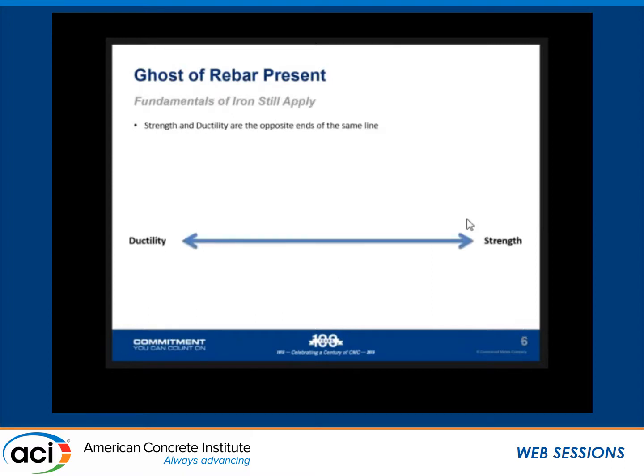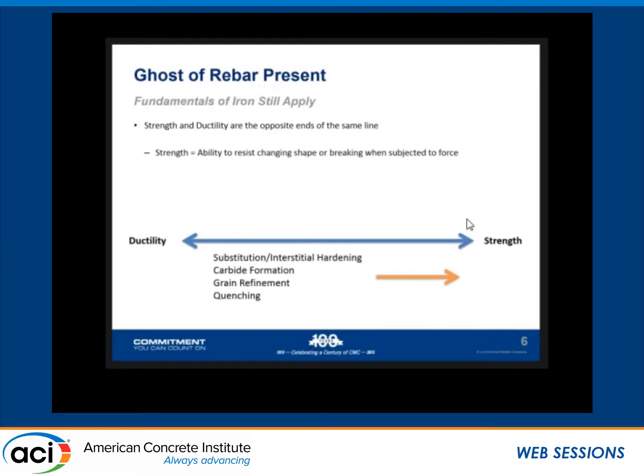So taking one last look at things, fundamentals of iron still apply. It doesn't matter how good we get as steel makers, you can't cheat physics. Strength, as far as a material is concerned, is the ability to resist changing shape or breaking when subjected to force. So things like substitution, interstitial hardening, carbide formations, grain refinement, quenching the steel, these things shift towards the right, towards strength. And in return, we're giving up something on the ductility side, because the definition of ductility is the ability to adapt to force by changing shape. They're direct opposites.